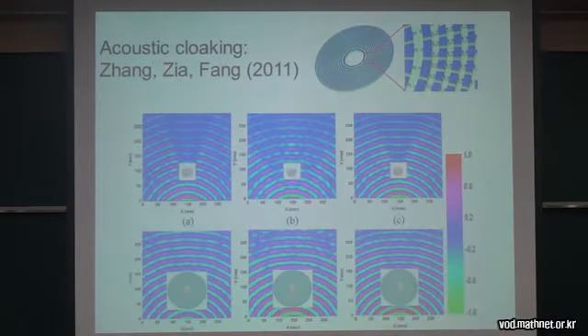And then for acoustic cloaking, Zhang, Zia, and Fang in 2011 obtained this sort of cloak here, and this is scattering of a disk with respect to acoustic waves. And again, you get a substantial shadow zone. If you put the cloak around it, you reduce the shadow zone considerably.